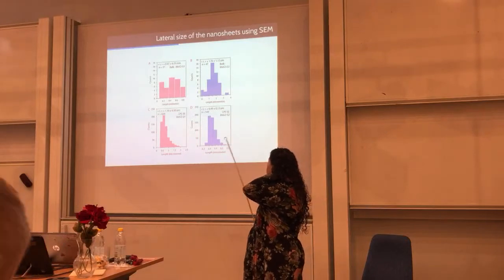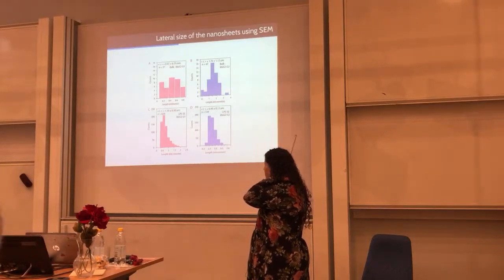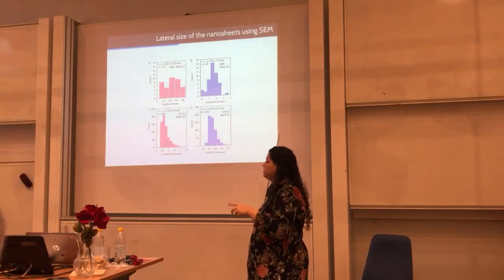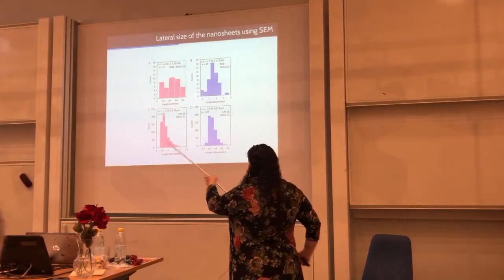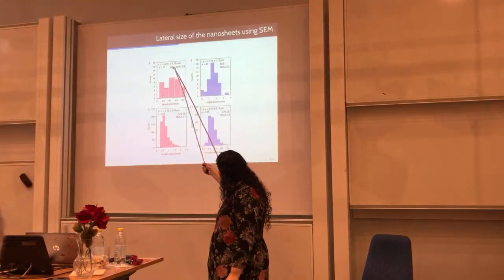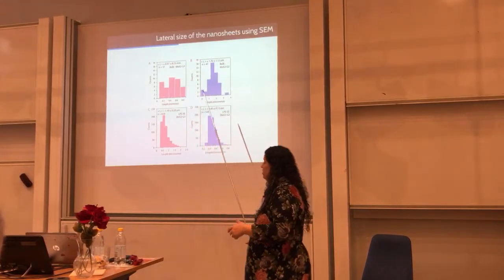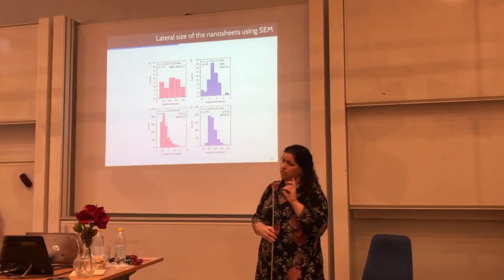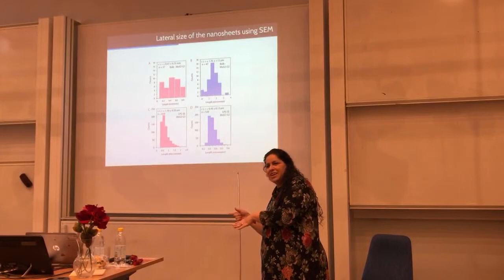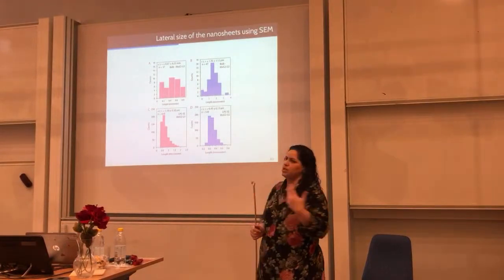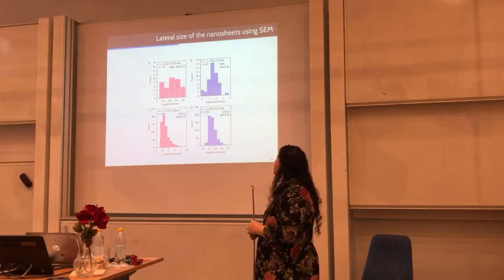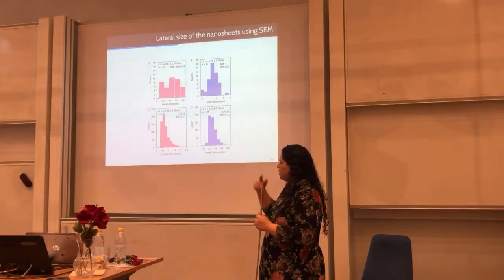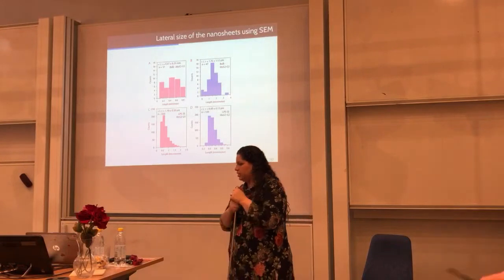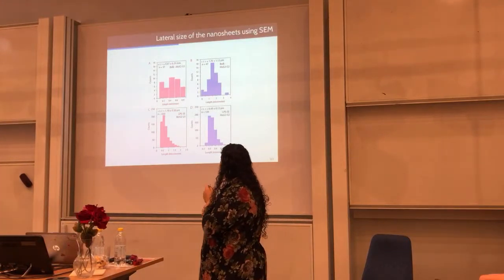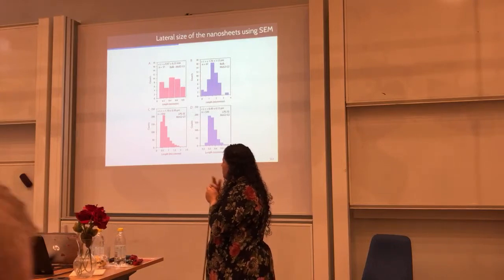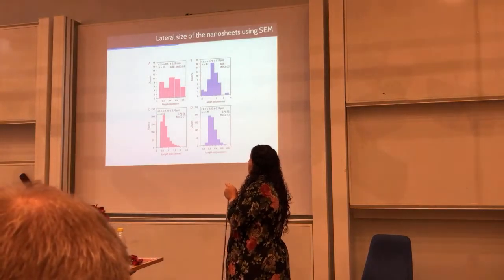Again, what I did in paper 3 is that I started with two different grades of molybdenum. One grade had a size range around 0.47 millimeter to start with. My goal with that was, if I start with a very big particle, can I end up with a bigger particle after exfoliation? The answer was no. It was more or less in the same range of particle size when you exfoliate. This was one question that Arlene O'Neill from the group of Jonathan Coleman put in her paper, but she didn't answer, and I tried to answer that question with my experiment.